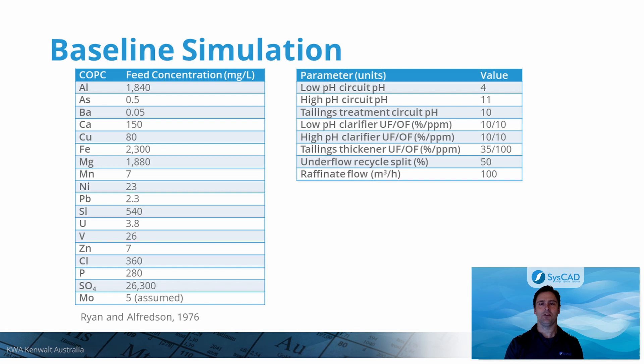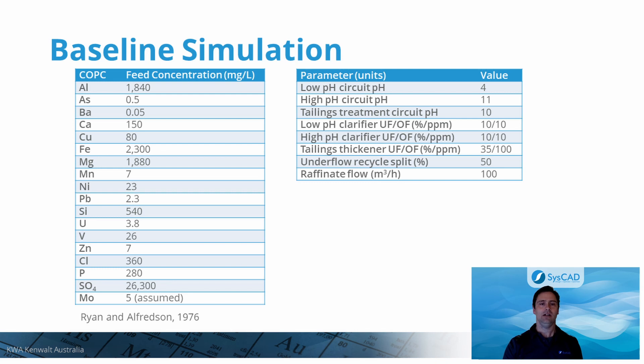Baseline conditions for the water treatment process are shown in these tables. Both tables represent typical values and are not specific to any mine site. The raffinate is predominantly a mixture of ferric, ferrous, and aluminum sulfate with a number of impurities. The concentration of molybdenum in the raffinate was not provided and thus a typical concentration of 5 milligrams per liter was assumed. Raffinate data from Ryan and Alfredson and full data references are available in the MetPlant 2023 paper.